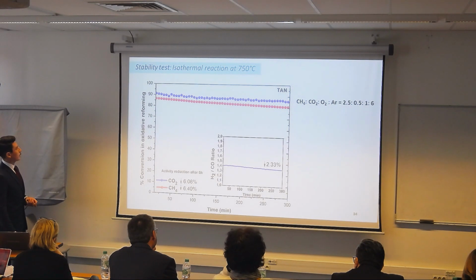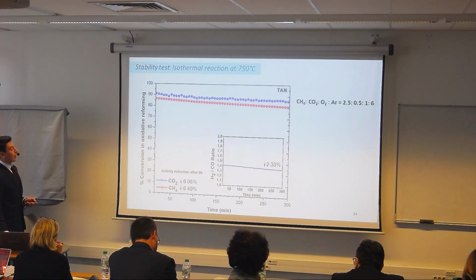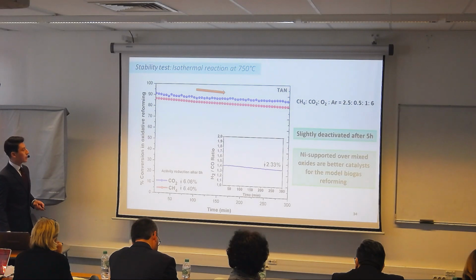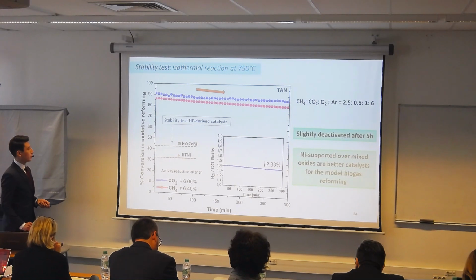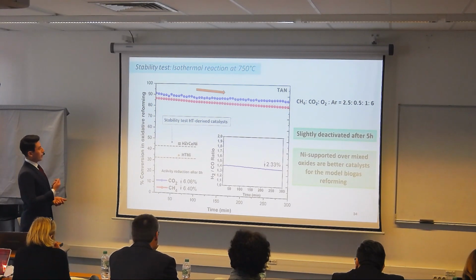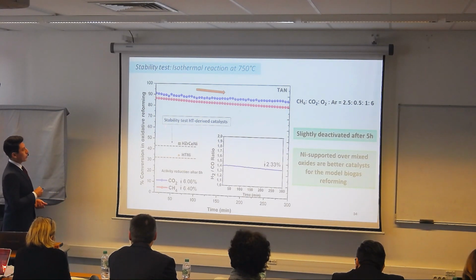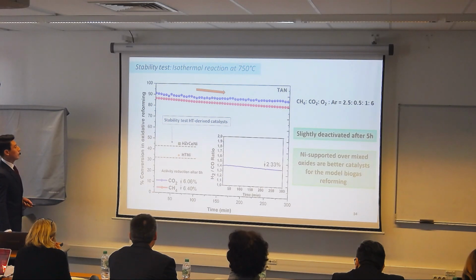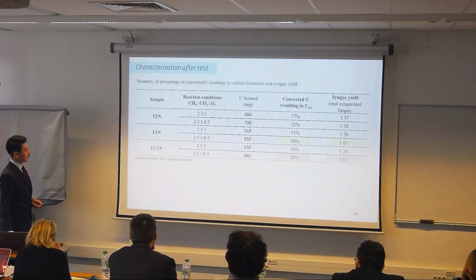So we tested through time in an isothermal test. We can see that there is a slight deactivation after 5 hours, and we can confirm that the nickel supported catalysts are very good materials when we compare them to the previous ones in the isothermal test. So these catalysts are promising for the oxidative reforming of biogas.